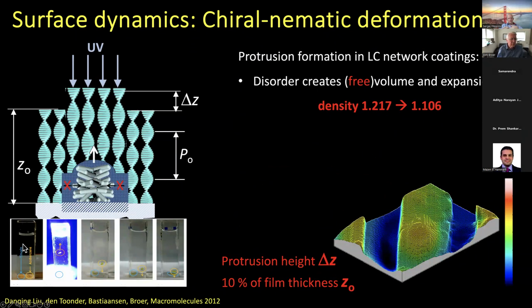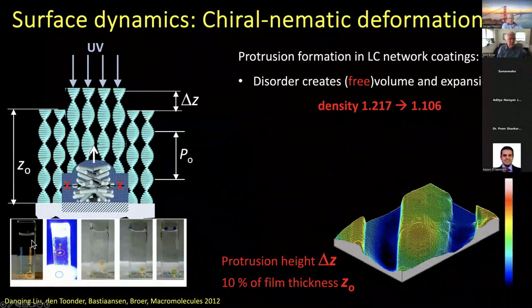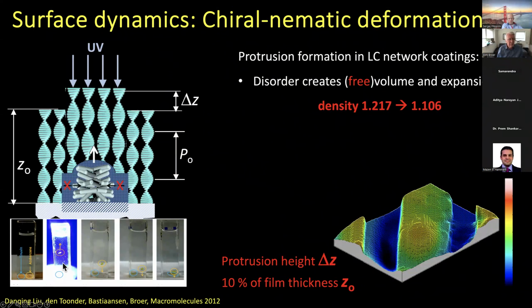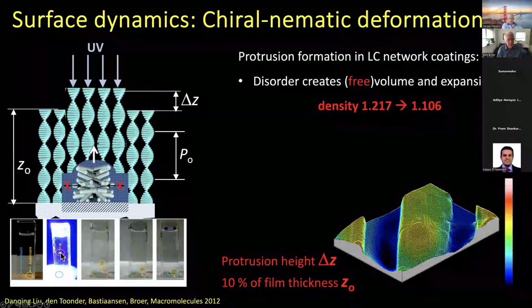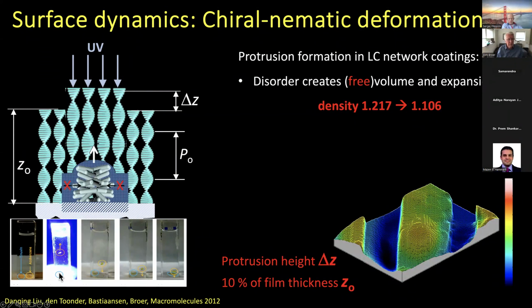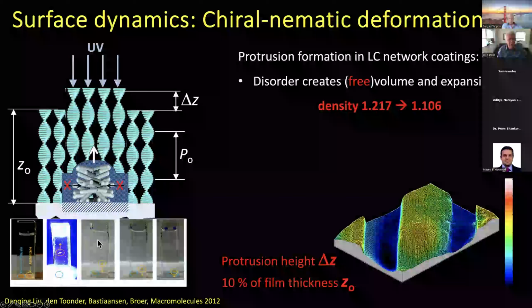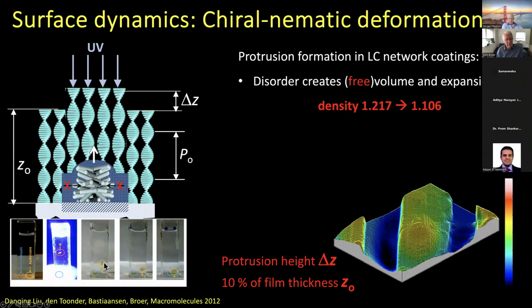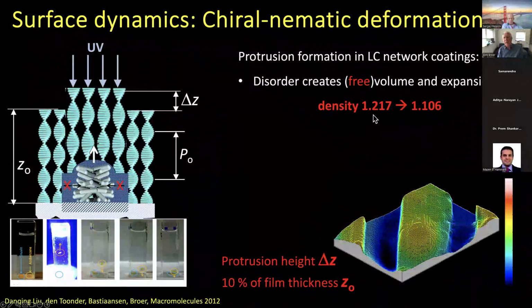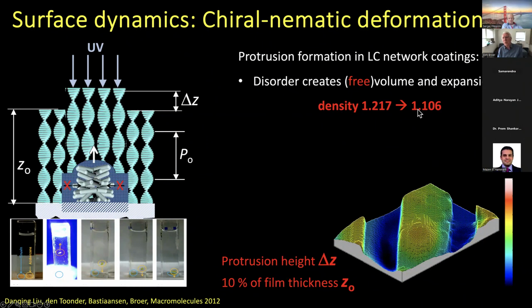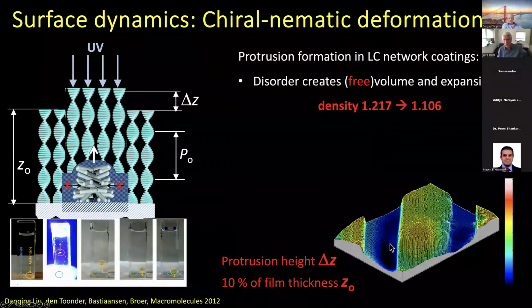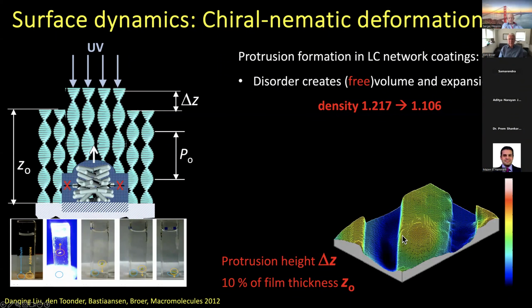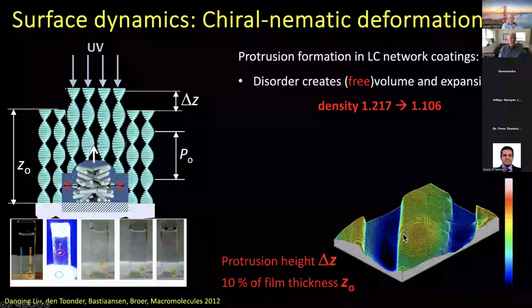The film is sinking. We have added some salt to the water to get the density right, and then you expose, and what you see is indeed that the density decreases and the film starts to float. The reference film remains at the bottom, and as soon as you switch off the light, it will sink again. And just by doing many experiments with different salt concentrations, you can estimate that the density changes from 1.2 to 1.1, about corresponding to the 10% deformation.